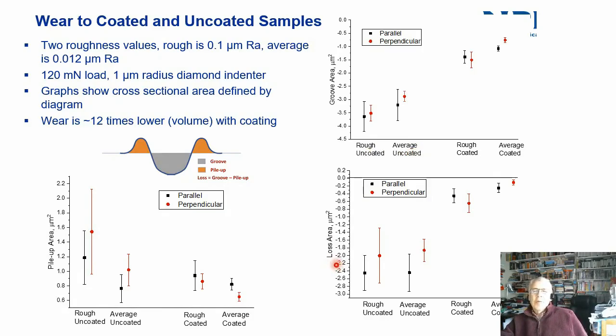In particular, if you look at the loss area, which is equivalent to the volume of material lost, you can see that there isn't any difference between the results for the rough and the average samples, but there is a huge difference depending on whether the sample is coated or not, and this is over an order of magnitude difference here.